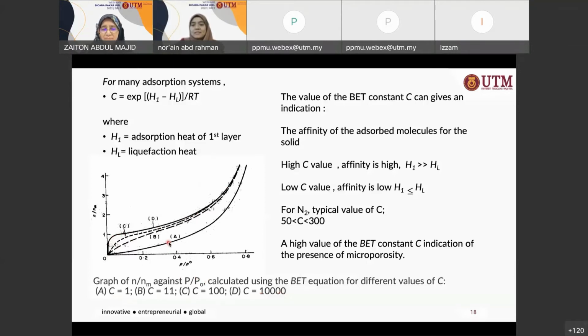Some of the literature also indicates that the value of this BET constant C can tell us roughly the shape of the isotherm, whether it is microporous, a combination with mesoporous, or non-porous. Okay, and also if you get a negative C, then something is wrong with your range of coverage of the BET, or maybe your sample is too small, or maybe your sample is not suitable for the BET surface area analysis.